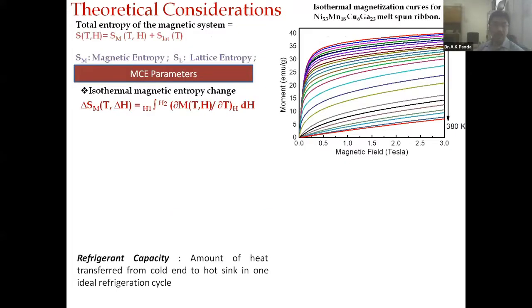So now let us again move to some of the theoretical concepts. On the right side, what you see are the magnetic moments, the magnetization plots. These plots have been carried out isothermally, and the temperatures range typically from 330 to 380 Kelvin. The moment goes on decreasing with increasing temperature.